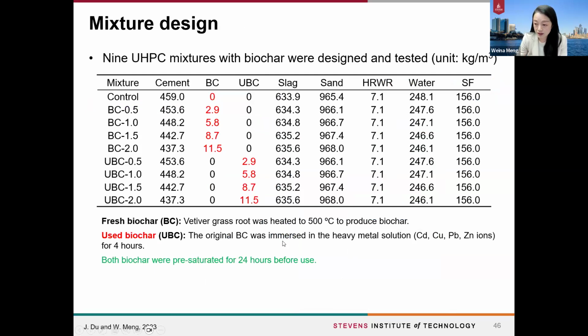So we investigate two cases of biochar. The first is a fresh biochar, and the second is we use the fresh biochar and immerse them into the heavy metal solutions for 4 hours. And we call this type of biochar a used biochar. And for both of the biochars, we pre-saturated them for 24 hours before use.